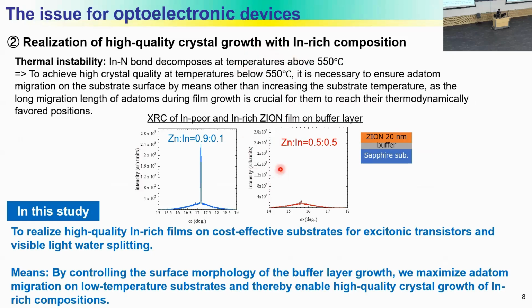These images show the XRC of an indium-poor ZnInON film and an indium-rich ZnInON film deposited at 300 degrees Celsius. Indium nitride bonds decompose at temperatures above 550 degrees. To achieve high crystal quality at temperatures below 550 degrees, it is necessary to ensure atom migration on the substrate surface by means other than increasing the substrate temperature, as long migration lengths of atoms during film growth are crucial for them to reach